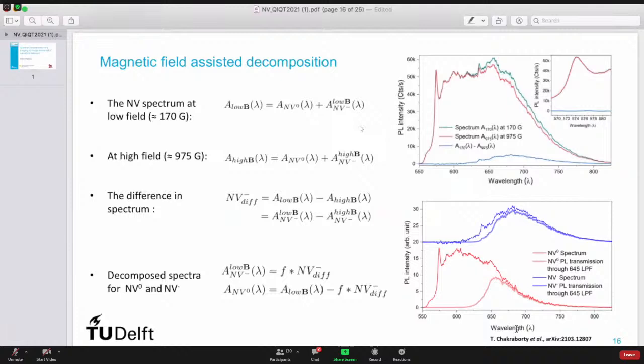Okay, so basically what we did, we performed the spectroscopy measurement, measured the optical spectrum under green 532 continuous wave excitation and for many different applied magnetic field strengths. We captured all the spectra many times, a few thousand times, and then averaged them to reduce any electrical or optical noise.